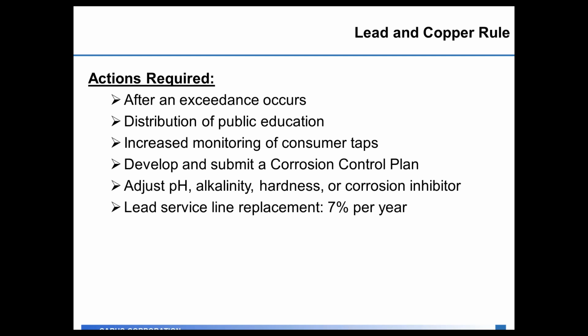That corrosion control plan can include how you would adjust the pH, the alkalinity, the hardness, or if you're going to add a corrosion inhibitor or change the dosage on the corrosion inhibitor. The lead and copper rule also lays out that you can choose an alternate way of compliance of doing lead service line replacement rather than doing a corrosion control plan. If you choose the path of lead service line replacement, the regulation states that you must replace at least 7% of the lead service lines per year until you have them all removed from your system as a path forward.